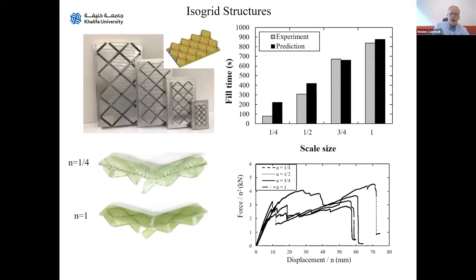And we've also used it to look at isogrid structures as well. Here we made 4 different scale sizes of isogrid molds. So everything here is accurately scaled, the groove, depth, et cetera. And we infused them using the vacuum-assisted resin transfer molding technique with my colleague here at Khalifa, Dr. Rahan Umar. And we looked at the time to fill these molds to actually produce these samples, and to investigate how our scale size influenced the fill time. And once again, we saw that they didn't fill according to how we would expect them to.